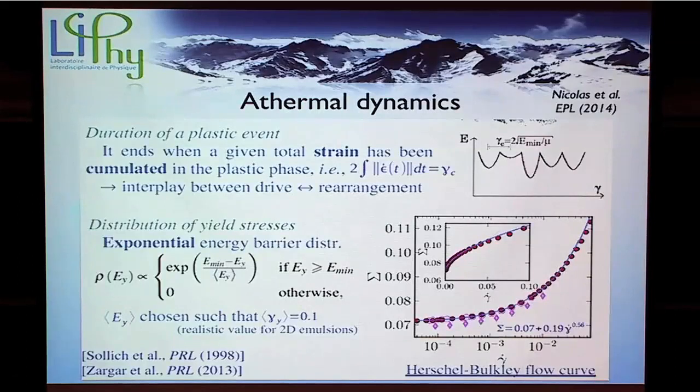Going to the next. Now I will come to the main part of the talk, which is the question of athermal dynamics. And this is a little bit dangerous, so be nice. So what we propose for the athermal dynamics in the yielding dynamics is that you will have a duration of a plastic event. To model this, there should be only two ingredients. There should be the fact that your system is structurally disordered, so you have a distribution of yield stresses, and you have a certain duration of a plastic event, so a certain dissipative time. And the interplay between the drive and this duration of the event will then lead to your nonlinear flow curve.